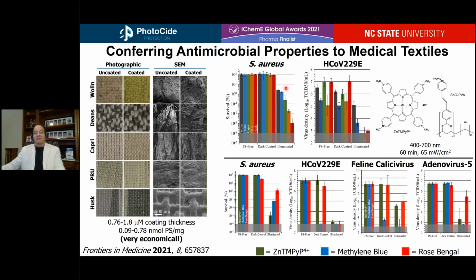Again, Staphylococcus aureus, these medical textiles, depending on the medical textile itself, it's always the same coating, but how much the coating was successfully sprayed onto the material, we get anywhere from 97 to 99.999% inactivation of the gram-positive Staphylococcus aureus, anywhere from 92 to, again, 99.999+% inactivation of human coronavirus, again, using this porphyrin-based photosensitizer.